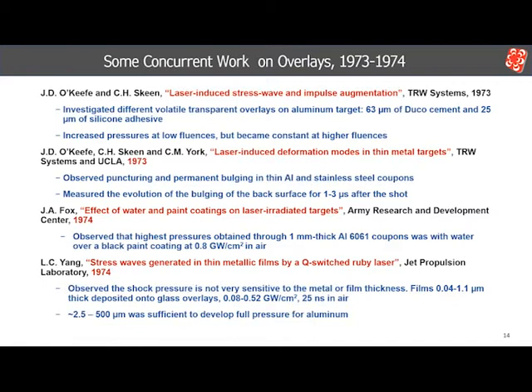Yang measured the pressures developed on a broad range of thin metal coatings deposited on glass overlays at low power densities, and found little difference in the pressure between the different metals or film thicknesses.